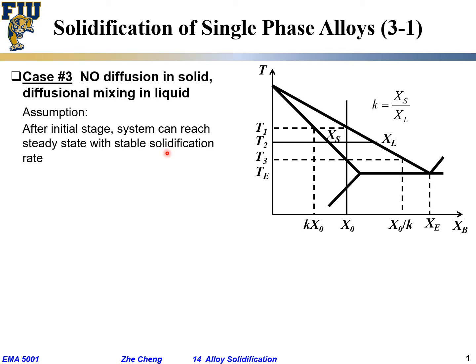But how fast is this rate? Quite often it will be determined — unlike the pure element case — by so-called diffusion. For a pure element, whether it's liquid or solid, it's the same composition, so there is not much composition change involved. But here, how fast you can solidify will be limited by how fast the stuff diffuses. Quite often, how fast stuff diffuses is even slower than how fast you extract the heat. It's cold enough, but somehow the diffusion is not enough. You are limited by diffusion, not so much by heat extraction.